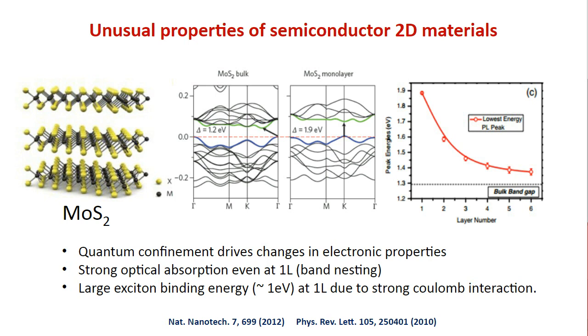As the figure on the right shows, 2-layer is about 1.6 eV band gap, 3-layer is about 1.4, and so on. And again, you might say that this change is small. You're changing from 0.5, 0.6 eV, maybe 0.7. Now in physics, this is a huge change. It's just like saying the height of a person changes from 6 feet to 10 feet. Now, that does not happen normally or ever to a single person. So it is as unusual as that.